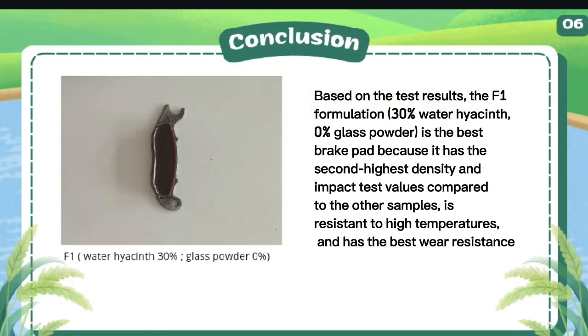Based on the results of the characterization testing, the F1 formulation, which is 30% water hyacinth and 0% glass powder, is the best brake pad because it has the second highest density and impact test value compared to the other samples. It is resistant to high temperature and has the best wear resistance.